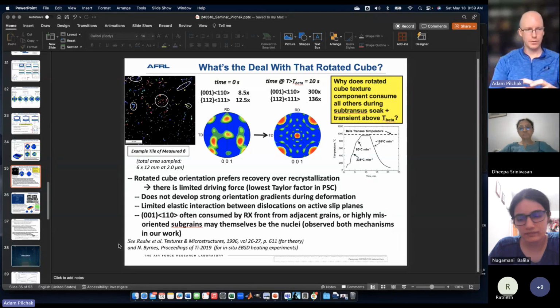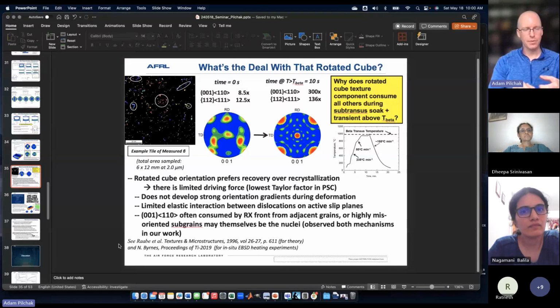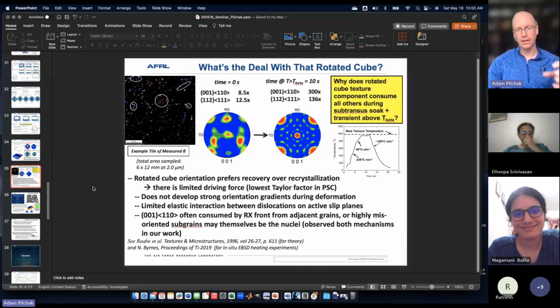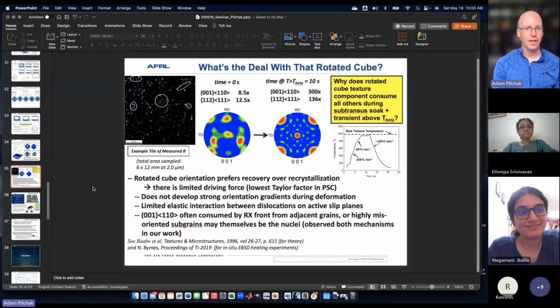So they looked at a relatively small area, and I forget if it was like 2000 frames per second EBSD or something like that. So a small area, pretty fast rates, but the video was amazing. I saw it at the 2019 World Ti Conference, and it showed exactly what we were saying about these rotated cube subgrains, just expanding at the expense of all the other beta phase orientations, concurrent with the alpha phase dissolving. They have a nice set of papers out on that. I don't know if the video ever got uploaded as supplementary information, but the video was beautiful.